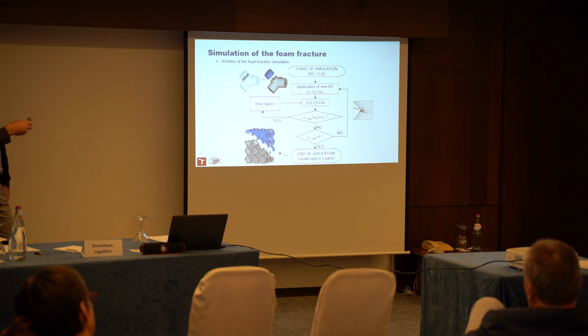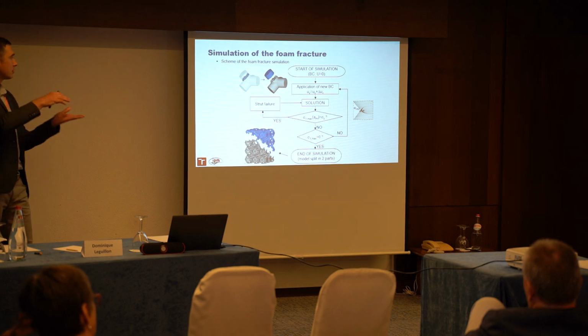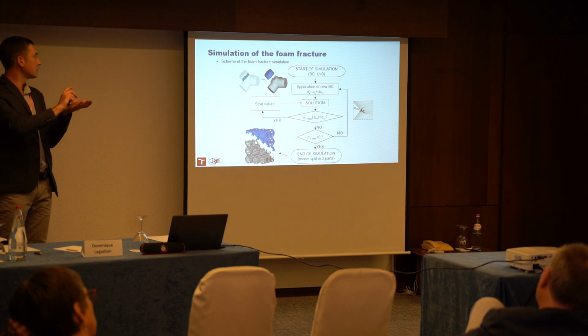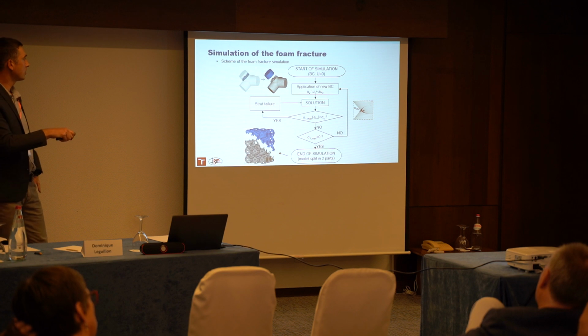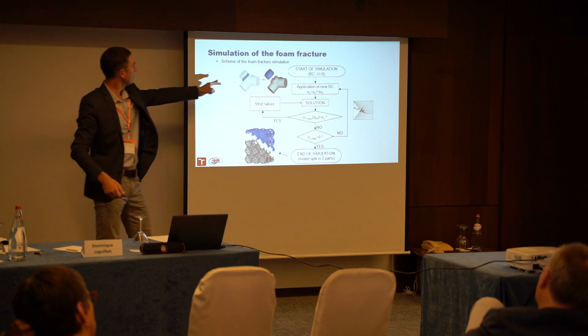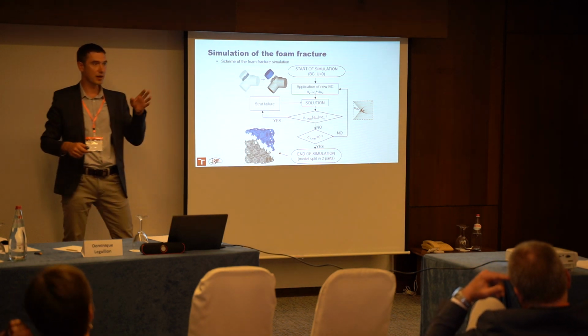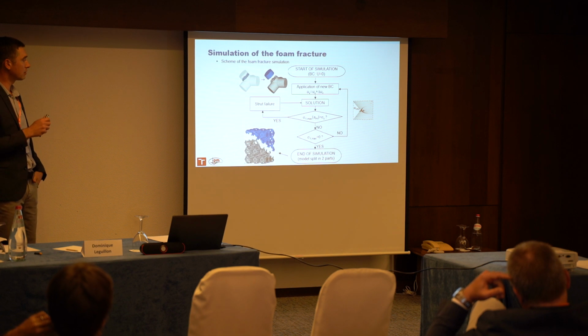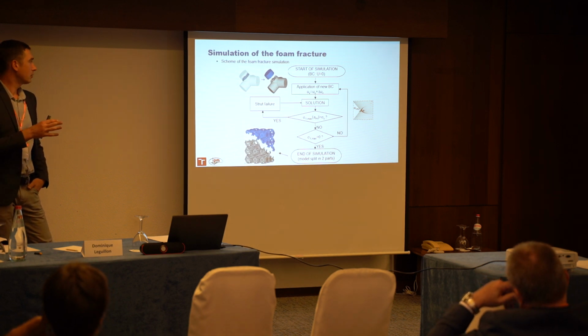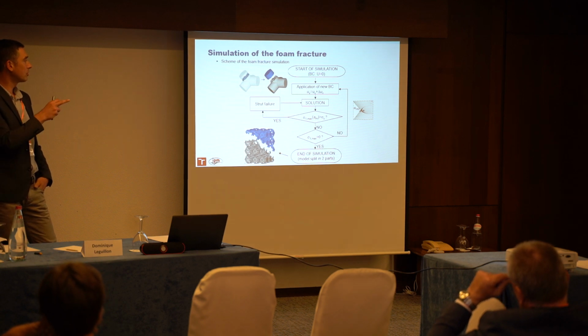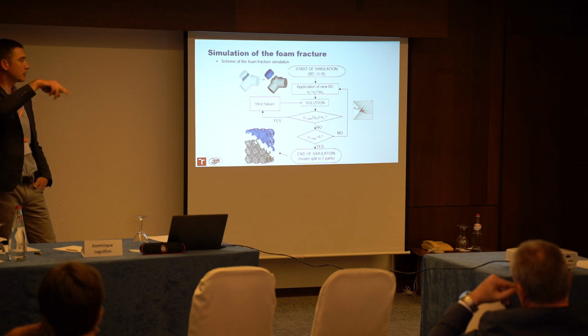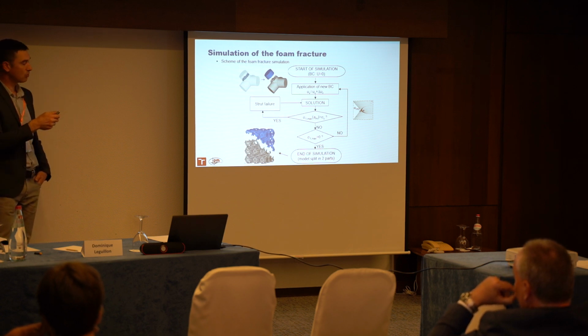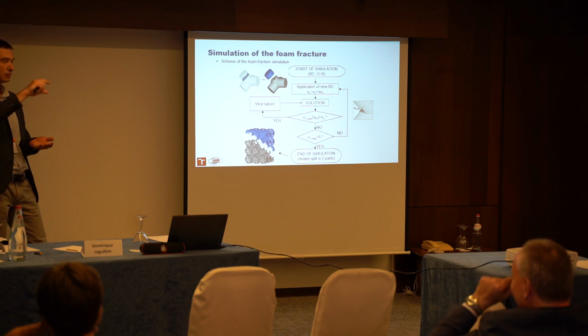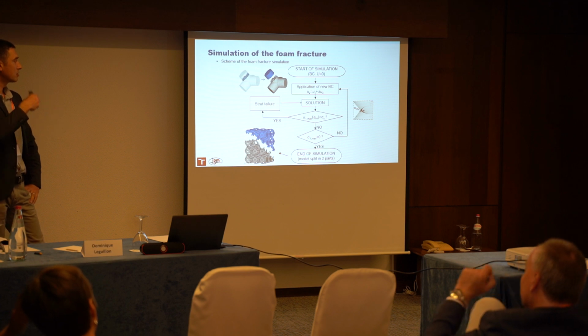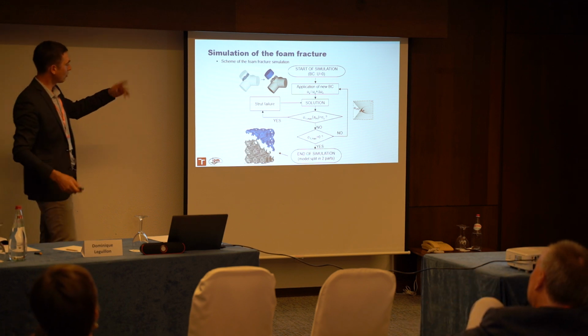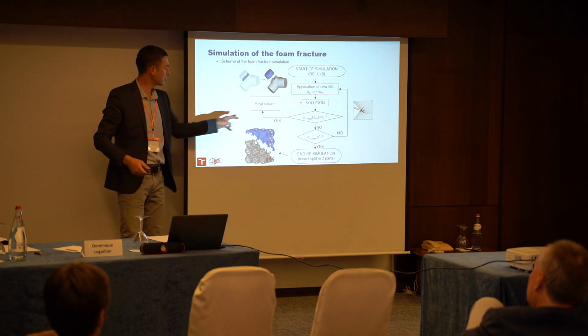The simulation procedure was the following. We started loading with some very small displacement. We check where is the high stress. We check in the depth of 13 microns what is the stress inside. If the stress was less than sigma c, we were sure that the fracture will not occur in that location. So if no spots in the whole structure were found, the load was increased, the displacement was increased, and in such an iterative procedure, in every step we check all potential locations of failure.